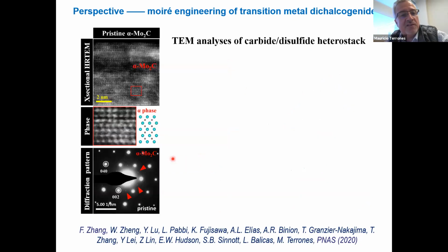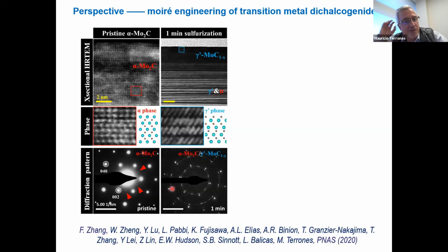So what do we see in this system? Here are the platelets of the alpha moly carbide. Again, you have this beautiful hexagonal pattern, and everything you can index, and you have a beautiful phase of this. So what happens when we do just 1 minute of sulfurization? This is very interesting, because in the diffraction pattern you have two families of rings, one inner ring and one outer ring. That means you have two phases, right? In this case, we have the alpha moly carbide, and then you have the gamma prime moly carbide. Gamma prime is a strained phase of moly carbide.